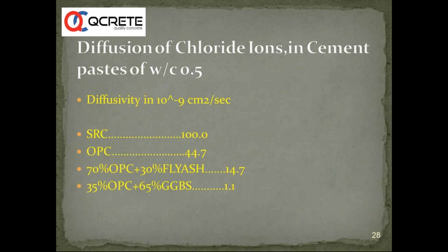This is another slide which talks about the resistance to chlorides. You can see OPC at 44.7, and then with 70% OPC, 30% fly ash. So this is a significant contribution, as we were talking about already. The RCPT values, or resistance to chlorides, is enhanced using fly ash.